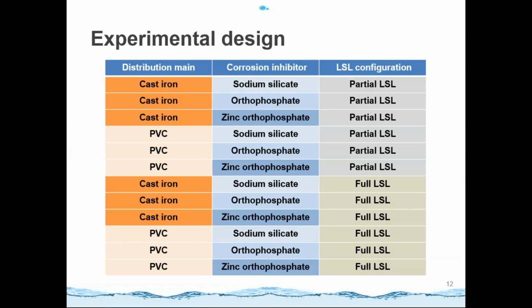As we can see, there are 12 lead pipes: 6 full lead service line pipes and 6 partial lead service line pipes. So with this experiment design, we can identify the difference caused by the cast iron pipe and the PVC pipe, and we can also tell the difference caused by the different corrosion inhibitors. At the same time, we can investigate the difference caused by the partial lead service line pipe and the full lead service line pipe.